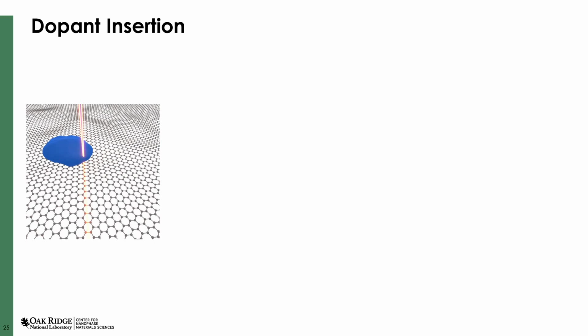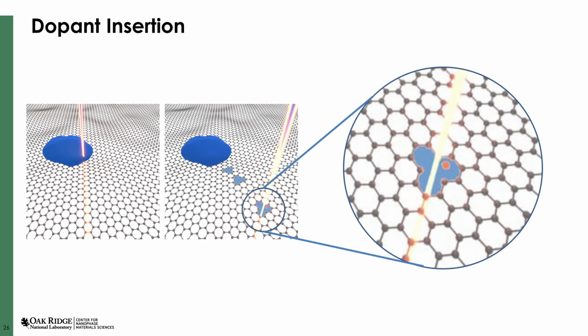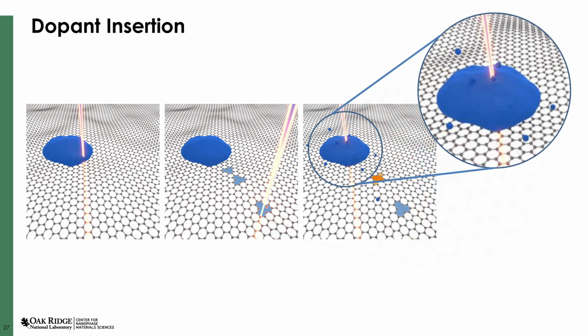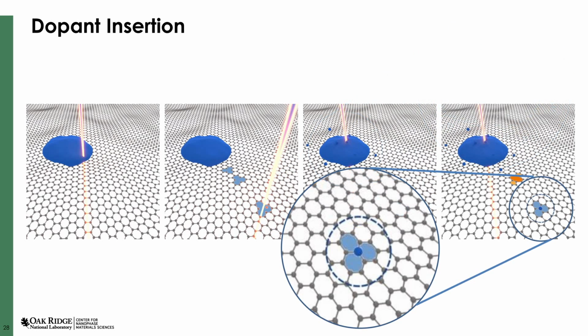So we take our electron beam and drag it across the graphene. If we operate the microscope with an accelerating voltage above the displacement threshold for graphene, we will start to eject carbon atoms from the lattice and form vacancies. Then, we move the beam back onto the source material and sputter single atoms off of it. These atoms can then diffuse around on the graphene surface, and when one of them reaches the vacancy site, it can form strong chemical bonds with the undercoordinated carbon atoms. We have then achieved deposition of a single atom.